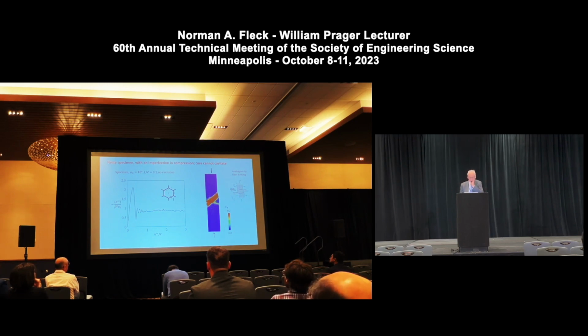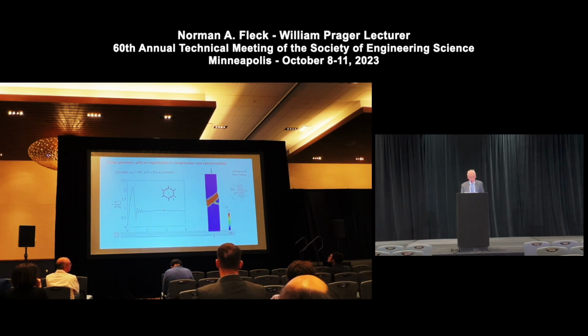I'll mention, because we've done a lot of work in this in the past in fiber microbuckling, when you look at this image, it looks in many ways like a fiber microbuckle. You get an inclined kink band. In this case, the material is deforming at constant volume, and you get propagation of the kink band first across the specimen. And then band broadening takes place. So this is exactly what you see in fiber composites. And the mechanics is rather similar. This instability is due to this strong softening and then lockup behavior.